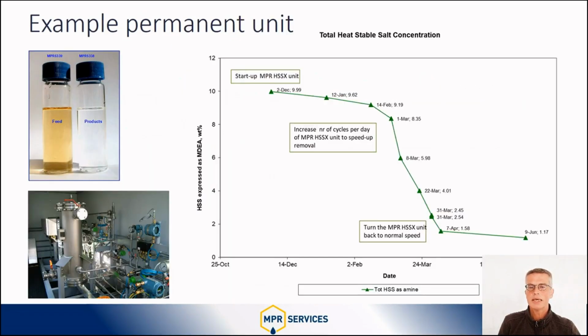A syngas plant had plans to increase the production. The amine system, however, was the limiting factor. Despite the fact that they replaced a lot of amine every 2 weeks, they constantly had a level of heat stable salts of over 10% as amine. That limited the capacity of the amine and the activator.